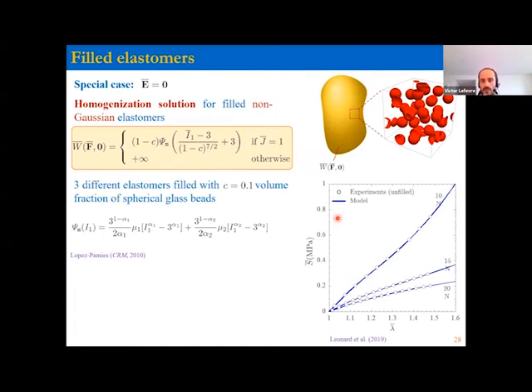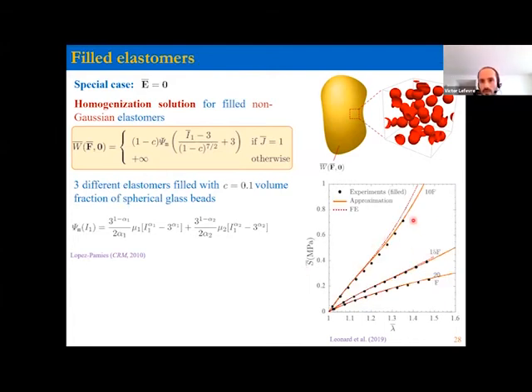And so there were recent comparisons with experiments. What this team did was to look at three different elastomers, so three different elastic responses. These are these three curves. And the blue lines are the fit of this model to this uniaxial tension data. They took these three different elastomers and made composites with the same volume fraction, 10% of large spherical glass beads. These are the results for the composites, the dark points. You can see the model in orange works very well, and also some numerics, the dashed red line. So there's a good agreement of the numerics, the model, and the experiments. That's nice. It's really remarkable that such a simple formula works that well for such a complicated problem.